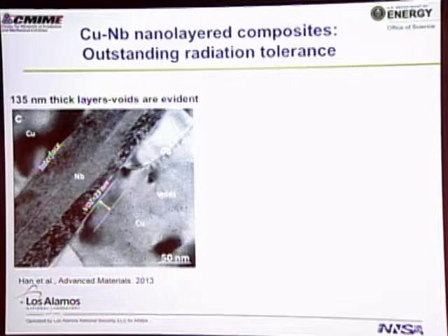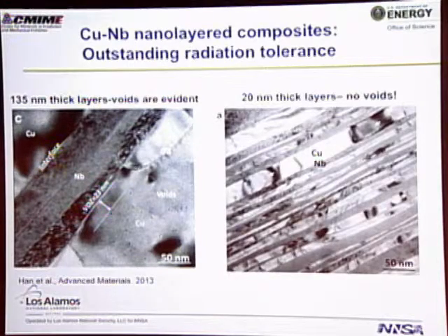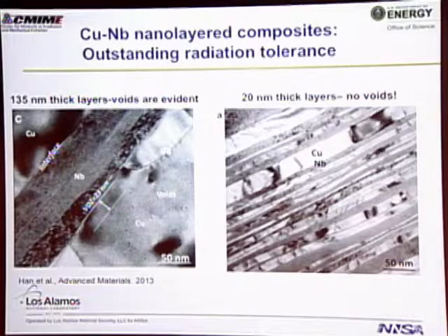So what happens if we just drop the layer thickness? Well, the answer is that you get no voids. You've added enough layers here and enough interfacial content that work as efficient sinks that now all of those defects are sucked into the boundaries and annihilated. You'll find a couple of voids in thick copper layers here, but all you have to do is just reduce that layer thickness a little bit more, and you've made this material radiation damage tolerant.